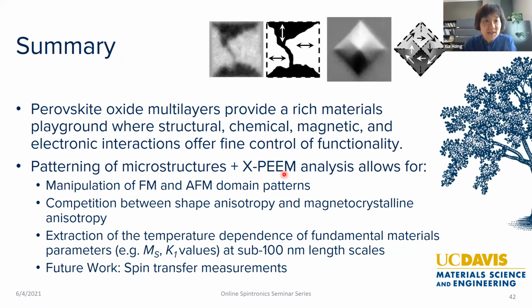Very nice talk. This is Xiaohong from University of Nebraska Lincoln. I have a question about the sensitivity and resolution of your technique. We showed that if we pattern LSMO on STO into nanostrips around 200 to 400 nanometers wide and 2 nanometers deep, you can put the sample in a very strange non-equilibrium strain state so that the anisotropy can be enhanced by 10 times. I noticed that your work is normally on really thick films, like 100 unit cells. But for 2 nanometers, basically 5 unit cells, is that something you think you can resolve?